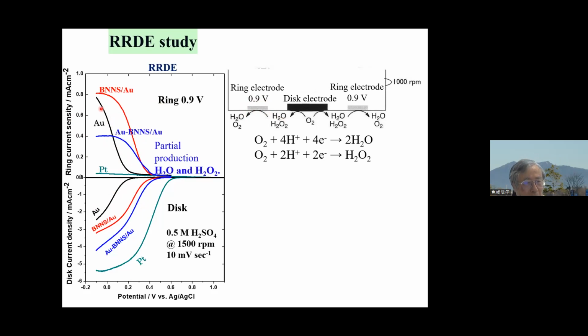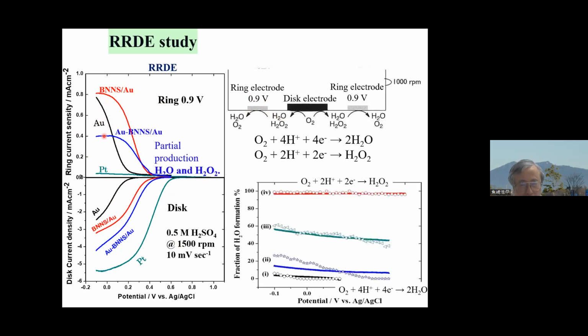In the case of the BNNS gold modification, the disk current increases, but the ring current also increases. However, by using the gold nanocluster modification on top of the boron nitride nanosheet, the disk current increases, but the ring current decreases. So we can calculate the fraction of H2O formation as a function of potential. This is platinum, almost 100%. This is gold. This is the boron nitride nanosheet modified gold, and this is the gold nanocluster modified boron nitride nanosheet gold. So it also improved the fraction of water formation, to 60%.